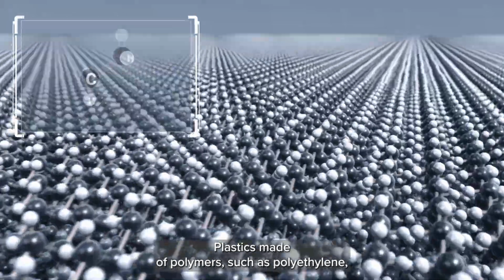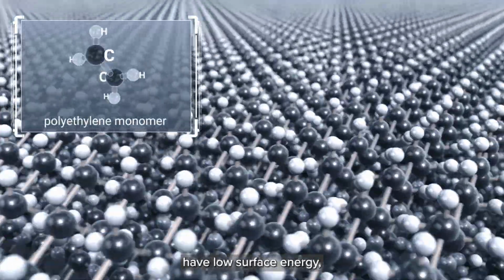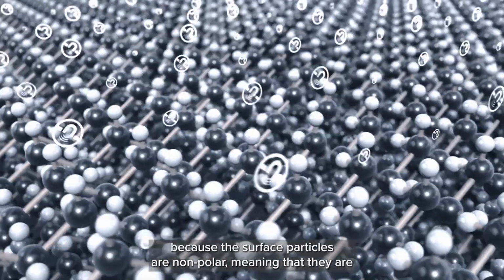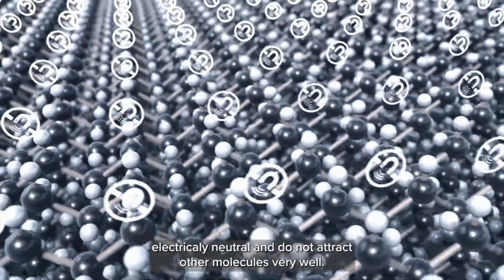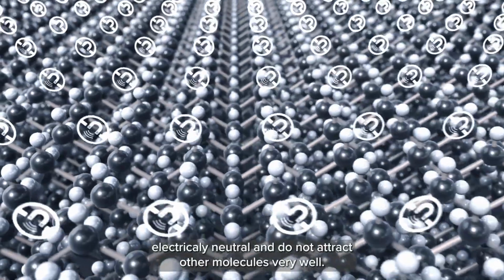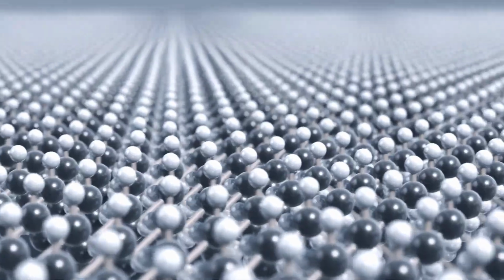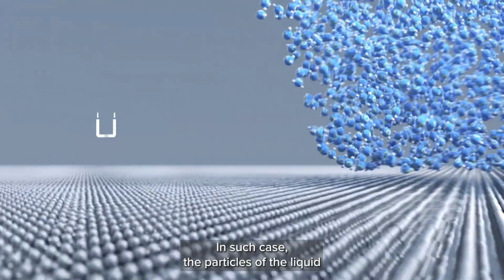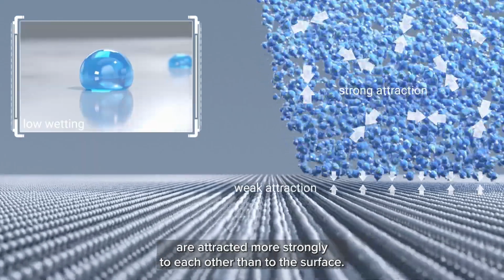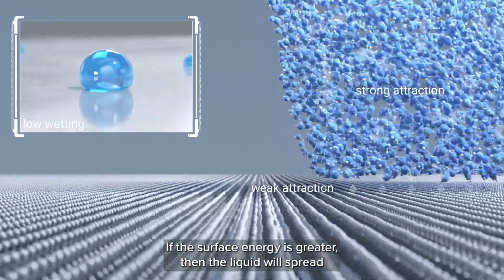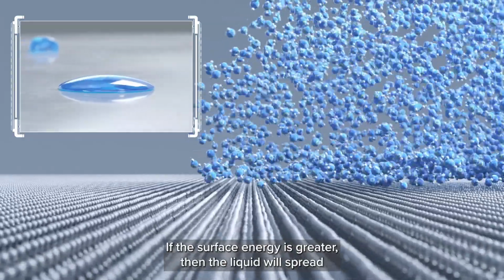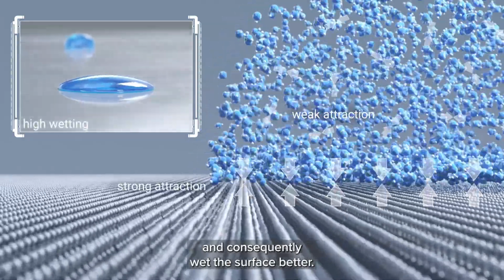Plastics made of polymers, such as polyethylene, have low surface energy because the surface particles are nonpolar, meaning that they are electrically neutral and do not attract other molecules very well. In such a case, the particles of the liquid are attracted more strongly to each other than to the surface. If the surface energy is greater, then the liquid will spread and consequently wet the surface better.